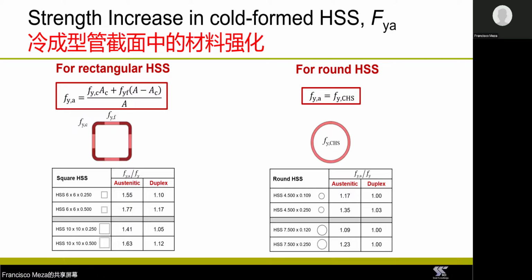Now, for square and rectangular hollow sections, the flat portions of the section might also show an increase in yield strength depending on the fabrication process. But this increase in yield strength will be less significant than the one in the corner regions. In a cold-formed round hollow section, you will also get an increase in yield strength, but this increase is going to be uniformly distributed across the entire cross-section because the plastic deformations in circular hollow sections are more uniform.